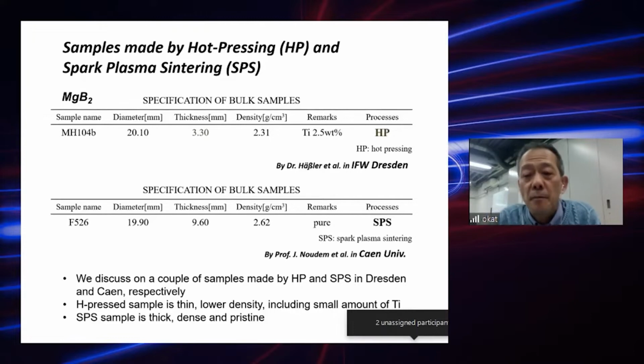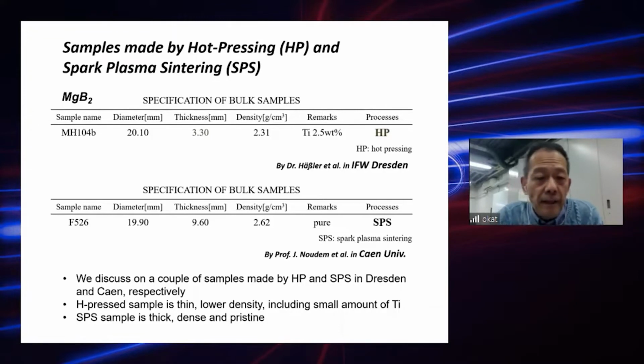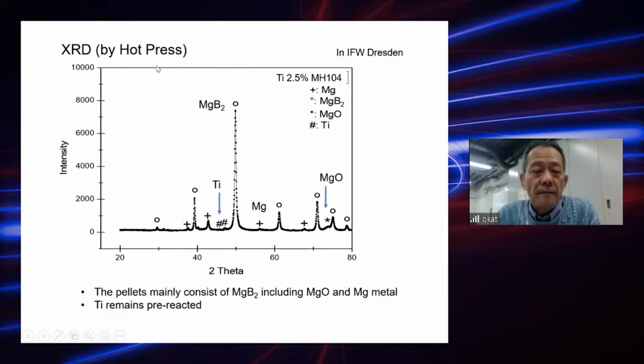In today's talk, I discuss a couple of samples made by hot pressing and spark plasma sintering, SPS, in Dresden and Caen respectively. The hot pressed sample is a little bit thinner and of lower density, including a small amount of titanium. The SPS sample is a little bit thicker, and dense, nearly the ideal density, and pristine.